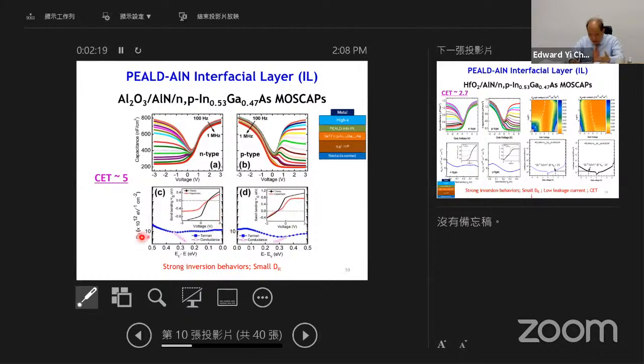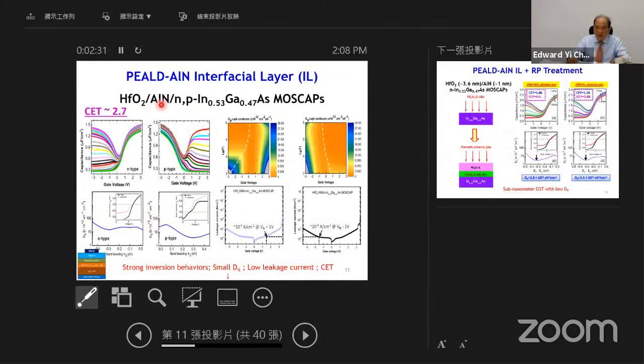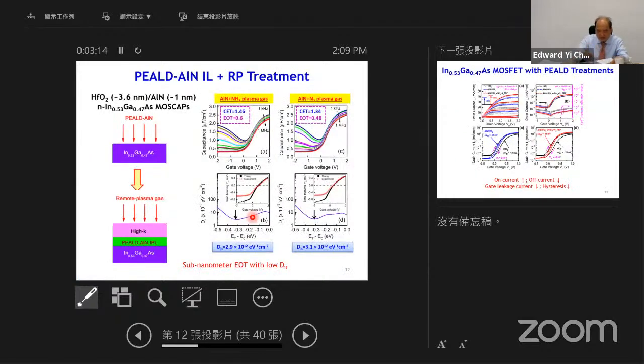The DIT range is 10^12, which can be verified from experimental and also from theory. Okay. And again, to reduce the EOT, we move the material from aluminum oxide to hafnium oxide. So this is a hafnium oxide, aluminum nitride, indium gallium arsenide MOSFET. And again, we have N-type and P-type MOSFET. And you can see that both have full inversion and very low DIT, both for N-type and P-type. And there's no Fermi level pinning and very low leakage current. So using this technology, you can achieve a very good indium gallium arsenide MOSFET, okay.